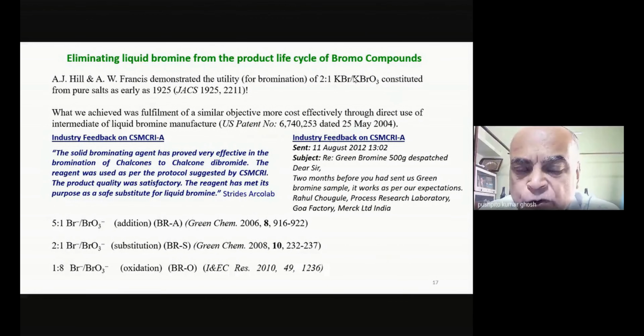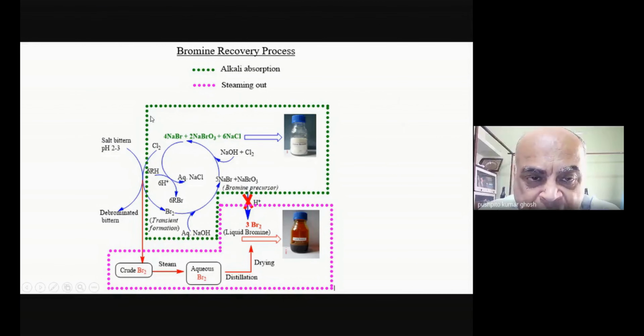Normally, you know that if I use Br2 and I try to do a reaction where I do an aromatic substitution to put a bromine atom into an aromatic ring, half of it becomes HBr. So your bromine atom efficiency is about 50%. Whereas with this, you'll get 100% bromine atom efficiency. What was interesting is that when we were looking at how bromine is made, one of the processes is what is known as the air blowing process. What you do is you first take your bittern, let's say, which has bromide, and you pass chlorine into it under acidic conditions. The chlorine oxidizes bromide to bromine and itself becomes chloride. So you get bromine out of it.